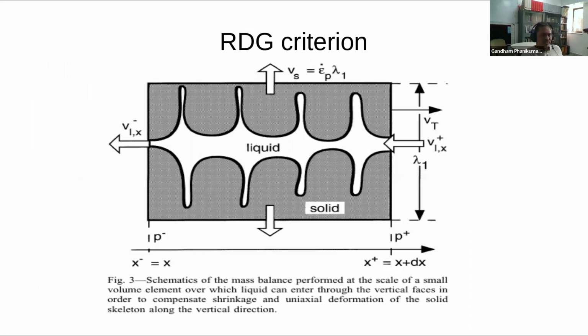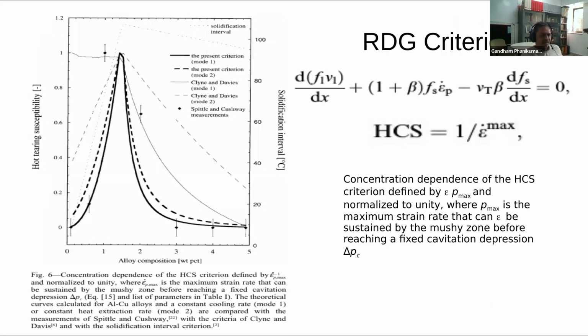Okay, so this is how the physics is imagined: the liquid is in between the dendrites and is trying to shrink, and the rate at which it will shrink because of solidification as well as the thermal contraction should be matched with the rate at which the liquid is entering the region. If there's any mismatch between the two, then you have a crack formation. That is the idea of how the mathematics has evolved, and with that, the criterion has been made.